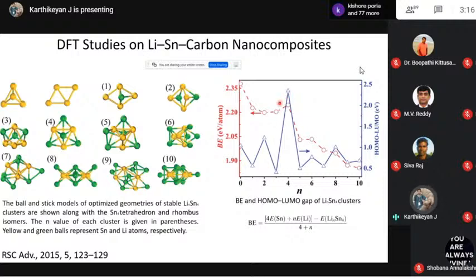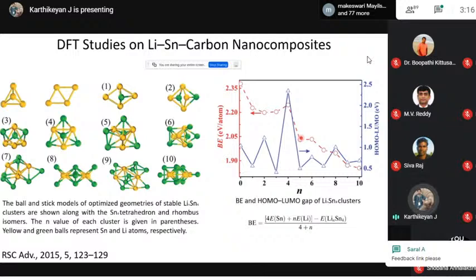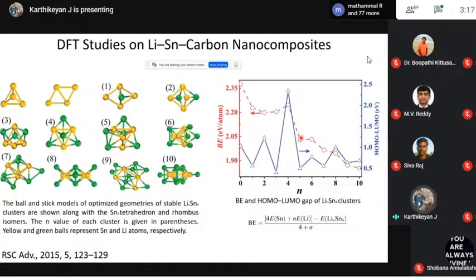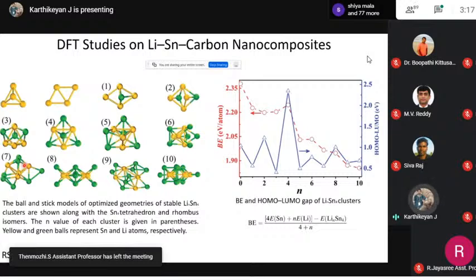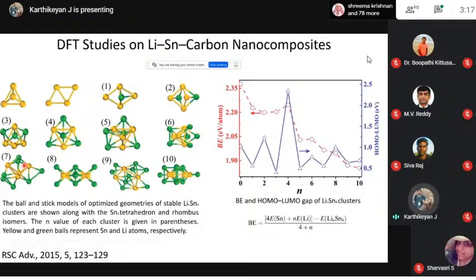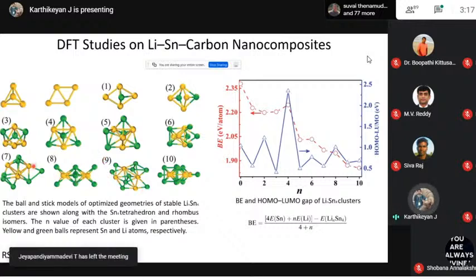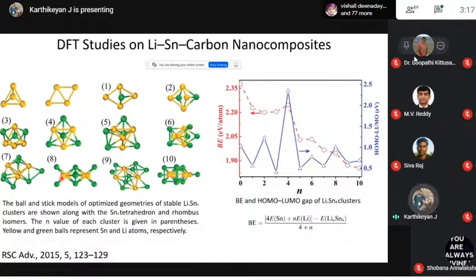When these Zintl forms are formed, all the bonding states are filled and the antibonding states are left free, so you get the maximum HOMO-LUMO gap for the system. That gives the highest stability for the Zintl phase. Then when you add further lithium atoms, as I told you, lithium always gives an electron to the material it is added to. So it donates more and more electrons into the antibonding orbitals of the tin atoms. Filling of antibonding orbitals reduces the bond strength, so the tin loses its tin-tin bond. To some extent it completely breaks the tin-tin bond; after 7 or 8 lithium atoms, we can say the tin-tin bond is completely broken.